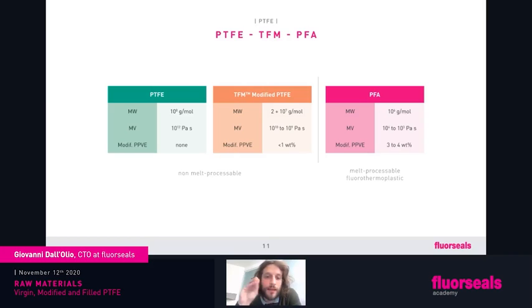Molecular weight of PTFE is 10 to the 8. When we are talking about PFA, that is the molecular weight. So the molecular weight is how long is that chain that we have seen before, the repetition of the entity, C2F4. On PFA, we have 10 to 6, so the molecular weight is reduced by 2 orders of magnitude. The viscosity for PTFE is 10 to the 12, so it's very, very high. It's not viscous, actually. For PFA, we have reduced the viscosity to 10 to the 3. So this leads the PFA to be melt-processable.